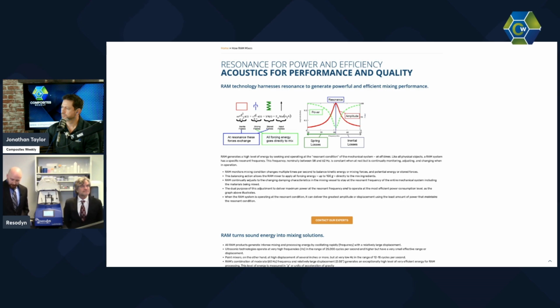And then, also the energetics industry is one of our biggest industries and where we got our start. Really, they're mixing sensitive materials that are extremely viscous. They were originally using bladed mixers at a very high torque, low speed, and mix times were often 24 hours to complete a batch of explosives. We're a high energy but low shear style of mixing, and we were able to mix these materials in under 20 minutes. So we save a lot of time for mixing. They've also been able to reduce their solvent usage in cleanup, and recycling solvents and any of the processes after using solvents are fairly expensive.